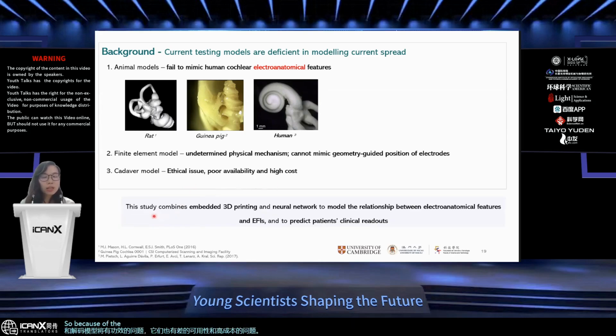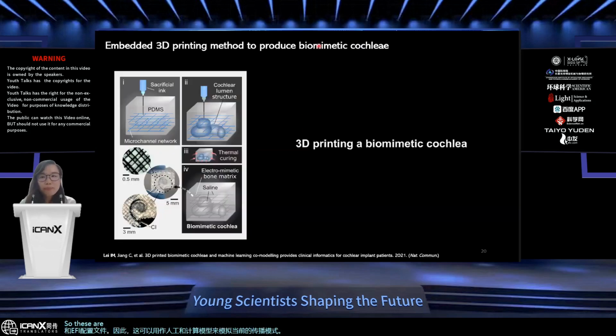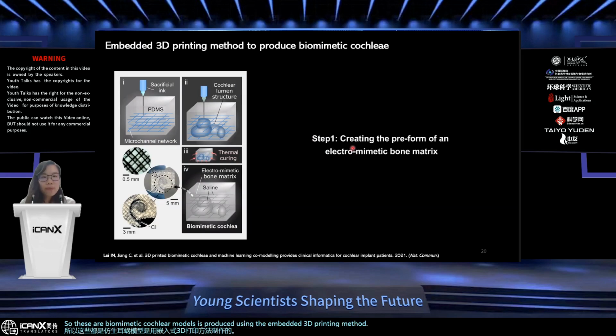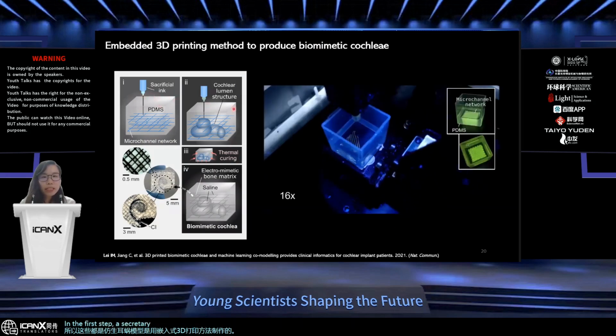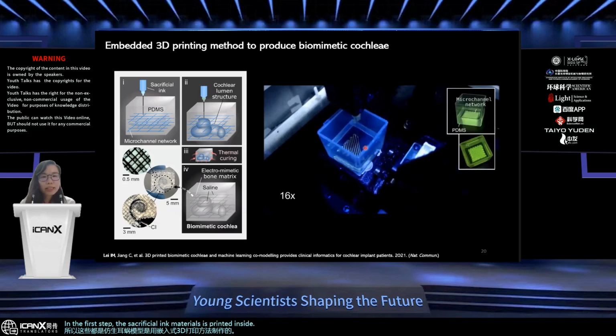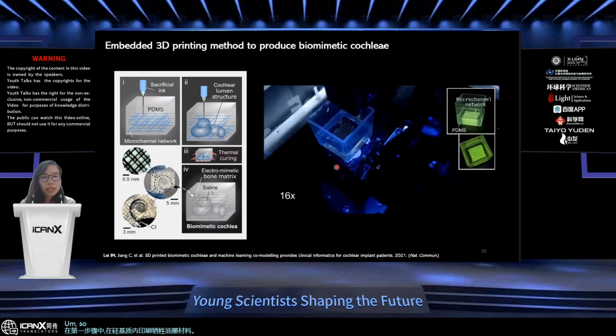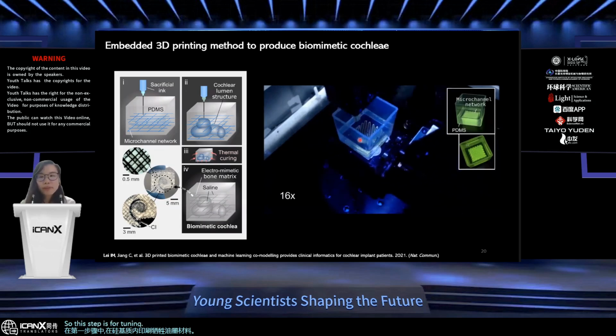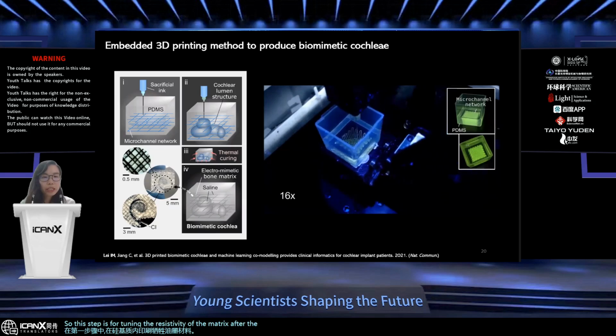Because of this, this study combined embedded 3D printing and neural network models to model the relationship between the electroanatomical features and the EFI profile. This can be used as an artificial and computational model to model the current spread problems. This biomimetic cochlear model is produced using the embedded 3D printing method. In the first step, a sacrificial ink material is printed inside a silicone matrix. This step is for tuning the resistivity of the matrix after fabrication.